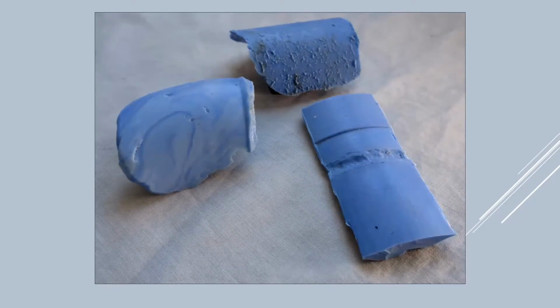This is a metrology grade putty again. So this one up at the top has some unusual circumferential corrosion in the pipe. I haven't figured out what caused it, but we're doing the metrology grade putty. We're putting it on that pipe because it's a failure analysis. This one over on the right hand side, what this one was for is there's a defect at that root reinforcement on that weld. And this one over here, they just didn't prepare the weld groove on the inside diameter correctly. So now we got that one done.